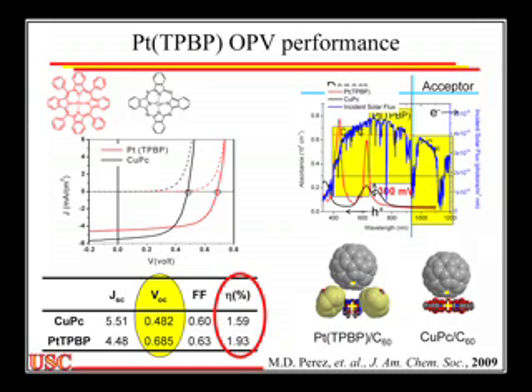It's very heavily distorted. And if we make close pack models, and this is not the kind of calculation that would be done in the Breda group, this is a PowerPoint calculation where I simply cut and pasted from two different calculations. Most of my time was spent figuring out how to get rid of the white box that surrounded the C60. I spent at least an hour figuring that out, which was more time than the total calculation time. But the point is that the phenyl groups here space the hole and the electron quite a bit further apart than the hole and the electron in CuPc C60. And so by doing this, I don't stop the back electron transfer, but I slow it down.